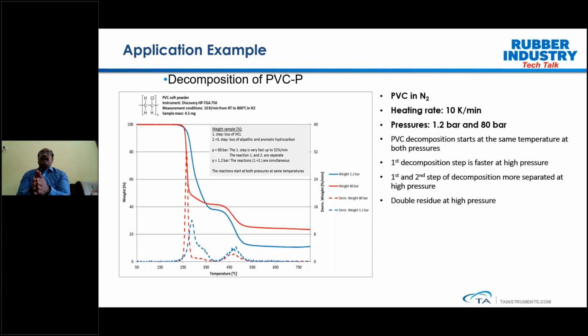So this clearly signifies how pressure actually speeds up the decomposition process. By using techniques like high-pressure TGA, you have the ability to study the material behavior not only with respect to temperature or time, but also as a function of pressure, which gives us a much deeper understanding of the material, and that will help you to design your processing when it comes to dealing with a particular polymer, and will help you avoid a lot of situations during processing of your particular polymeric material.